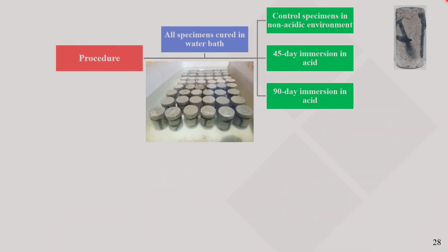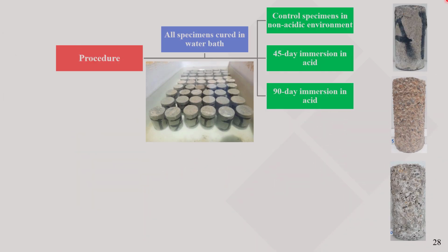Testing conditions: the tests were performed under 3 conditions. First, the non-acidic condition. Samples were tested directly after curing in a water bath. Second, the 45-day acidic condition. 1/3 of the samples were tested after 45 days of immersion in acid. Third, the 90-day acidic condition. Another third of the samples were tested after 90 days of immersion in acid.